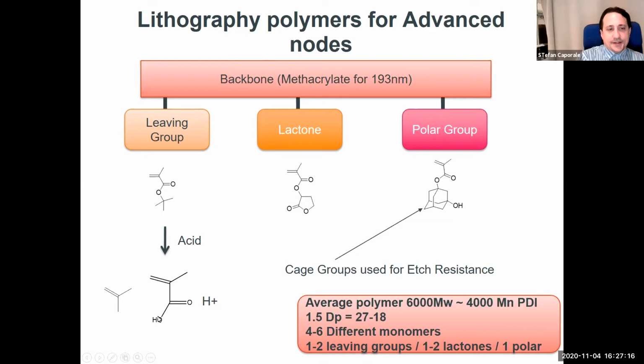This having a lower pKa, about 4 versus the phenol, means you need less of this in your material. A lactone, these are common cage groups used for a bunch of different reasons. This functionality here will ring open once you get into your developer and make more acid. This allows you to not have your film redeposit back onto your wafer, as well as this does provide hydrogen bonding control to control your diffusion of your acids and bases through the film, as well as adhesion to your underlying substrate. And finally, it also can be in a cage format, which does provide some etch resistance.